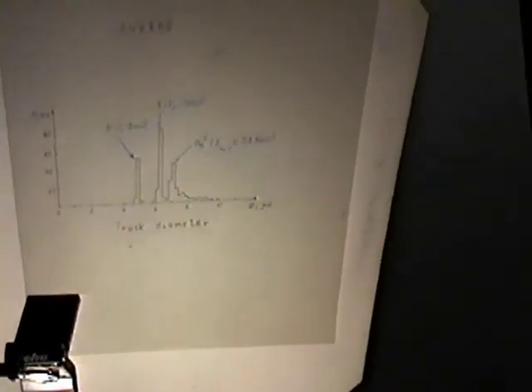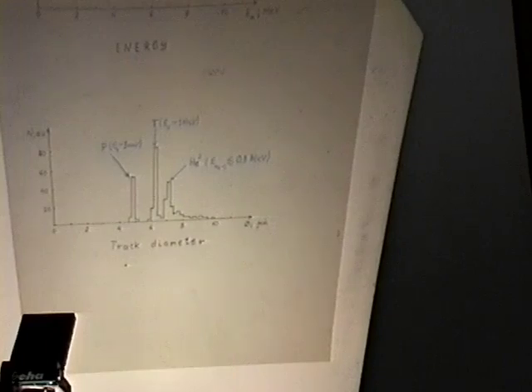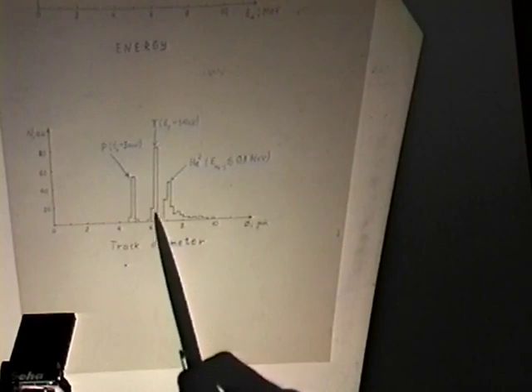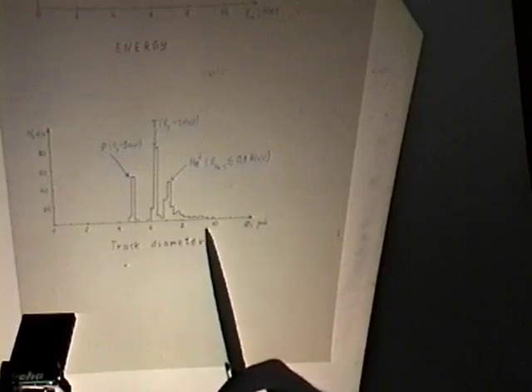According to the dependence of track diameter on ionization losses of the particle, the higher the ionization losses, the larger the diameter, it is possible to suppose that the peak in the region near 5 microns corresponds to protons with energy 3 MeV. The peak in the region 6.4 microns corresponds to tritons with energy 1 MeV, and the peak in the region 7.2 micron with long tail up to 10 micron corresponds to helium-3 nuclei with energy less than 0.8 MeV.